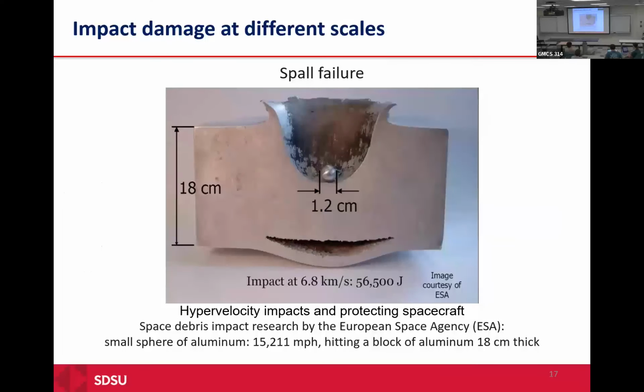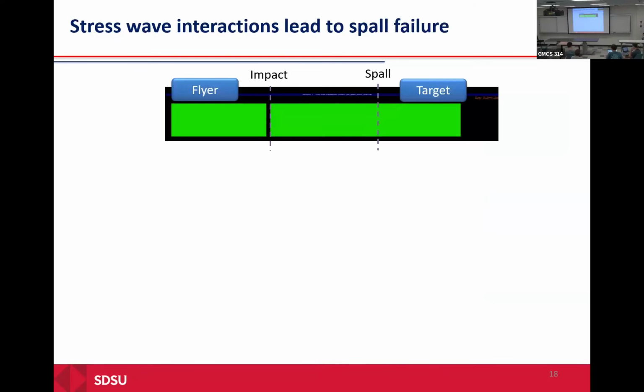Here is one of the samples that has been sent by the European Space Agency. It shows some of the space debris hitting an aluminum plate, and you can see that this is a small sphere hitting the aluminum plate. The plate can avoid the penetration of the bullet, but on the other hand, it cannot avoid the effect of wave propagation. Those waves come through the plate, and at some point they cause some failure in the material that can be seen here, and we call it spall failure. Then we want to see how we can predict or control this spall failure.